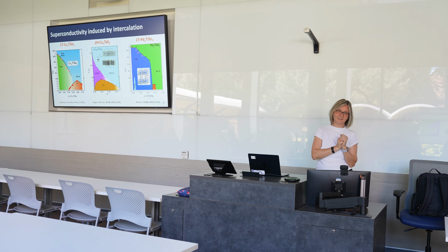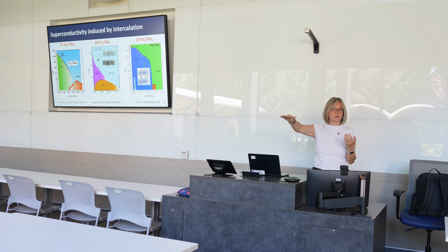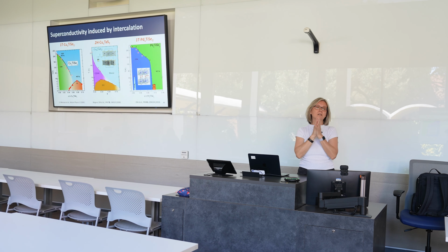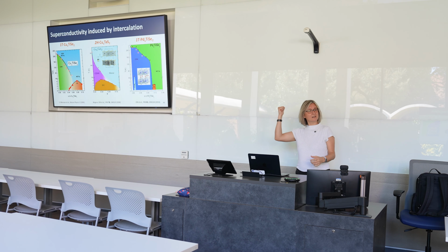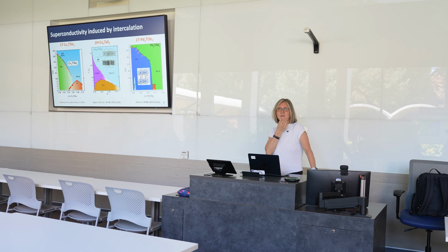I have a point. Again, because if I wanted to measure it, I would have to cut the boundaries perpendicular or close to perpendicular. There's no way to measure it continuously as a function of composition, right? So I only see it in one composition, which tells me that there's a very narrow phase that has it. I don't know a lot of the details of what kind of charge density wave that is. But a lot of materials like the niobium triselenide that I showed you can have multiple CDWs, right? And again, the superconducting dome in this case only has 2 points, right?